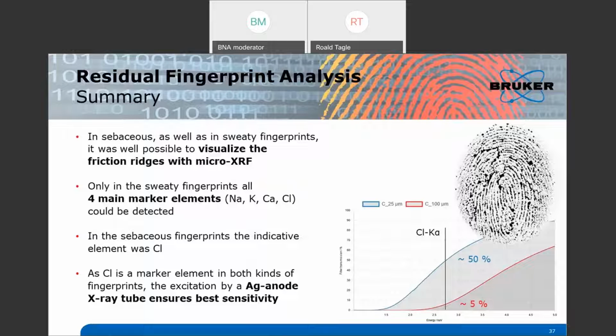Yeah, and with that, we start to summarize our findings on the residual fingerprint analysis. In the sebaceous as well as the sweaty fingerprints, it was well possible to visualize the friction ridges with the micro-XRF, especially for the element chlorine. In the sweaty fingerprints, all main marker elements, which we consider to be sodium, potassium, calcium, and chlorine, can be detected, and the sebaceous fingerprints had only chlorine for us to detect. Since chlorine is abundant in both types of fingerprints, we would suggest a silver anode if the specific application is the detection of fingerprints.